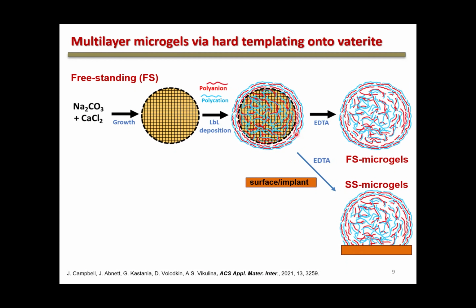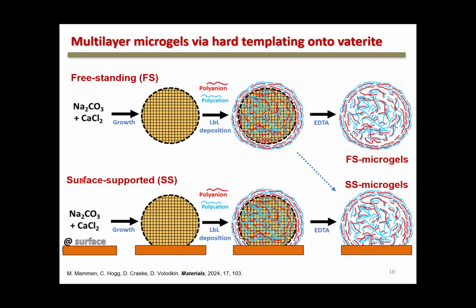So this is what we published a few years ago, that in the presence of a solid surface, when you get rid of the calcium carbonate core, they may stick to the surface during their formation, basically in one step. And then recently we asked ourselves what would happen if the whole procedure is done in the presence of the surface. This would correspond to this sequence of actions underneath this slide. This was work done by a couple of master students. Actually, this was a master student thesis, and it was very successful.